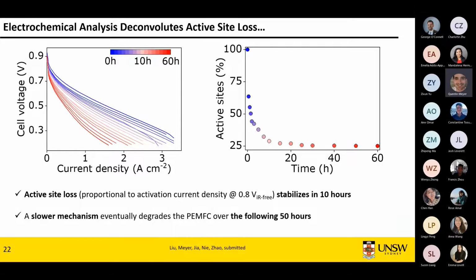Now going further into current measurements. We captured the polarization curve literally 16 times. Every time we stop, we capture the polarization curve. We can see very quickly in the first 10 hours, you lose about half the power, the performance, and then in the next 50 hours, about the other half. So one thing we can look at from the polarization curve is the active site loss, which, according to a few good papers published recently, is nearly proportional to the activation current density at 0.8 volt after ohmic correction. So that's what we did: plotted a line at 0.8 volt, corrected with the ohmic resistance, and this is what we get, which is the active site retention.